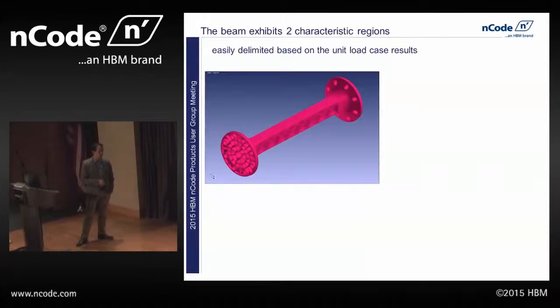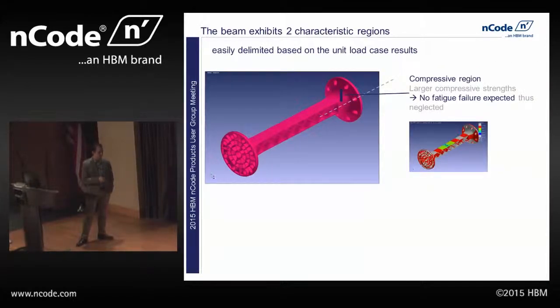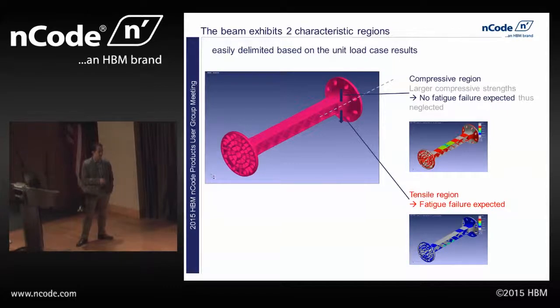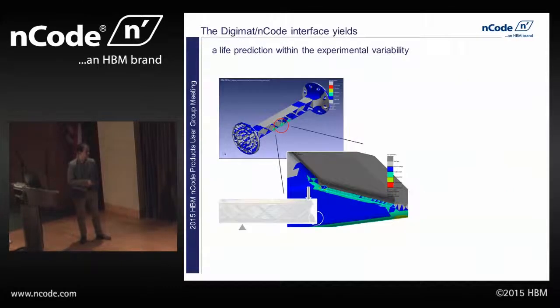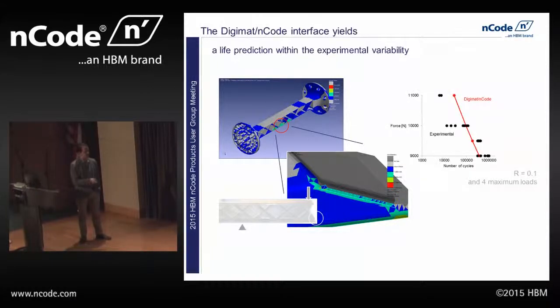So then when we move to our analysis, instead of looking at the compression side of the beam, we're really going to focus on the tensile side of the beam. So if we look at that tensile side of the beam after we bring that damage model into nCode along with our stress strain that we generated in our finite element analysis, we can then look at the fatigue life prediction that happens. You can see that it's highest right in that area where we see the beam failure actually happening. And then we can go ahead and plot those against the experimental results.